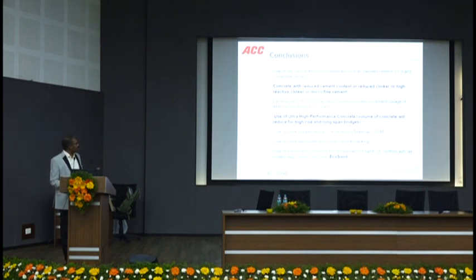And to summarize, how to improve the service life of the structure: use material which has less carbon emissions, like highly reactive clinker, or usage of blended cement, usage of supplementary cementitious material, or less cement per cubic meter of concrete, or usage of high performance concrete like high strength concrete, where you can drastically reduce the cement content or reduce the size of the column. Also use more supplementary cementitious material.